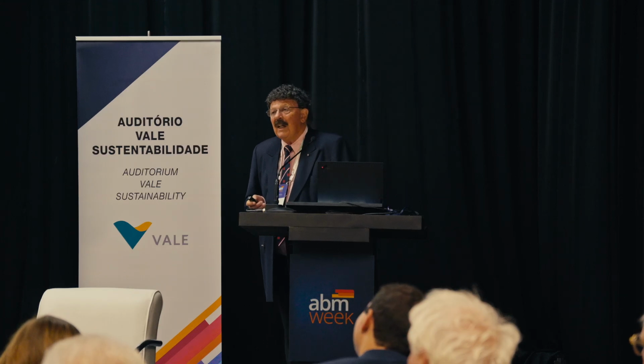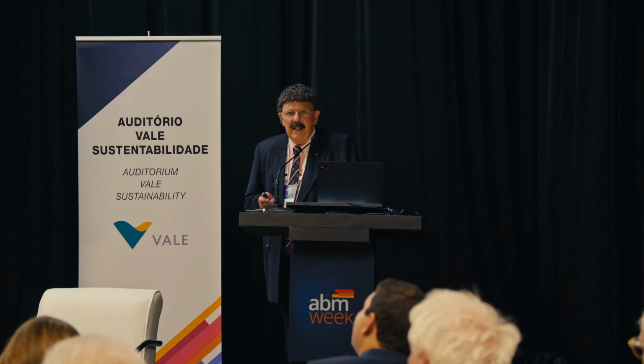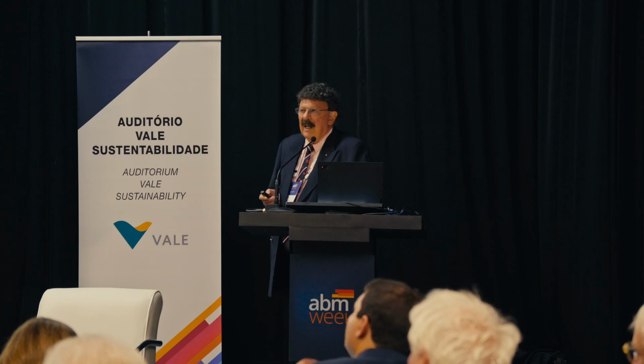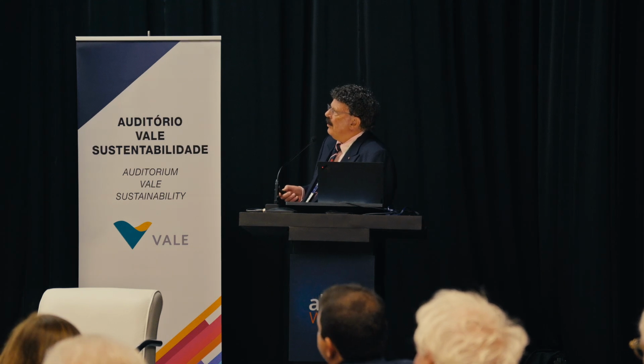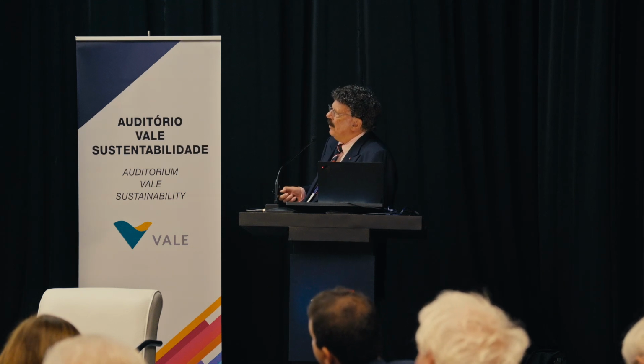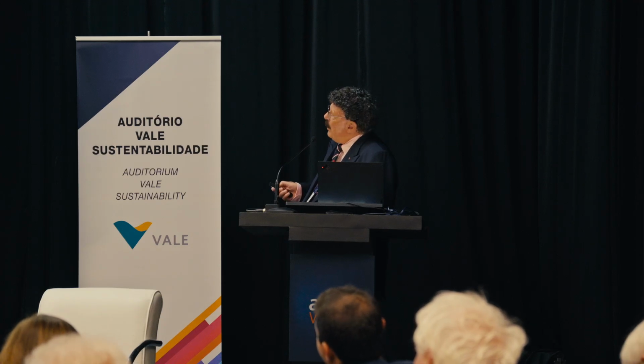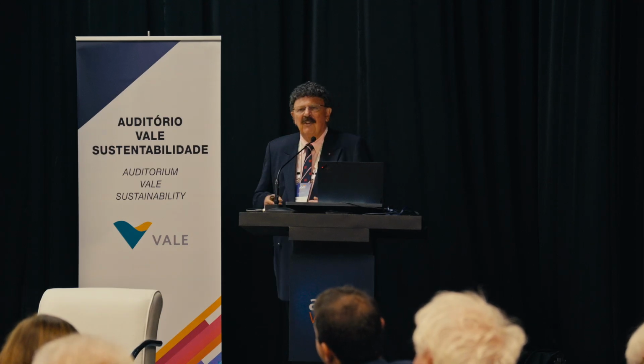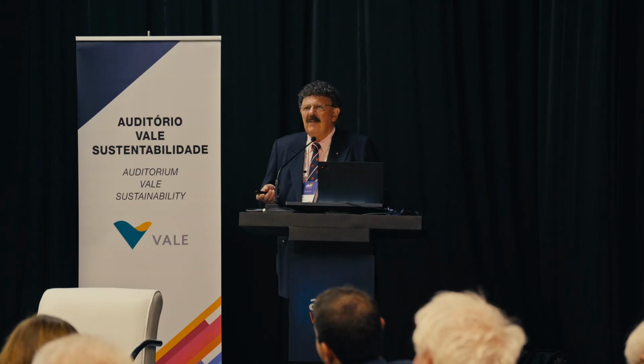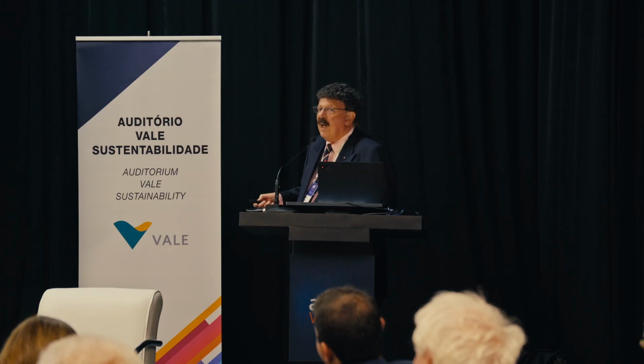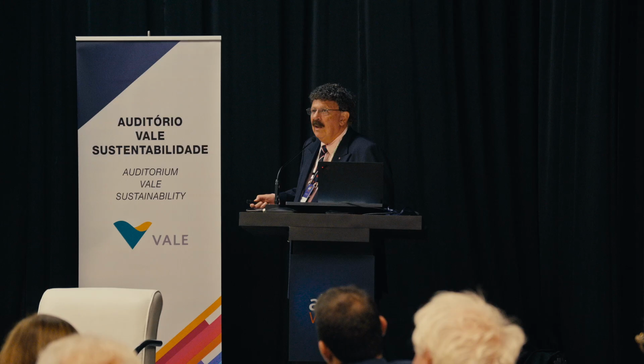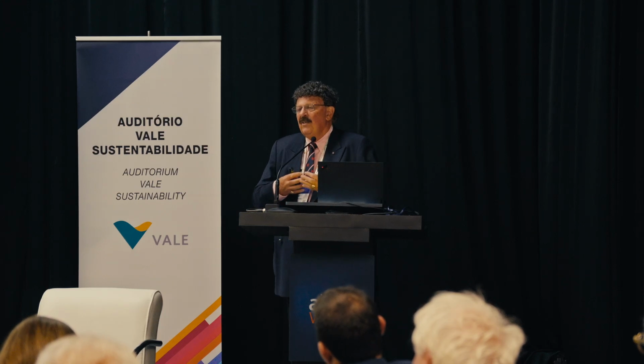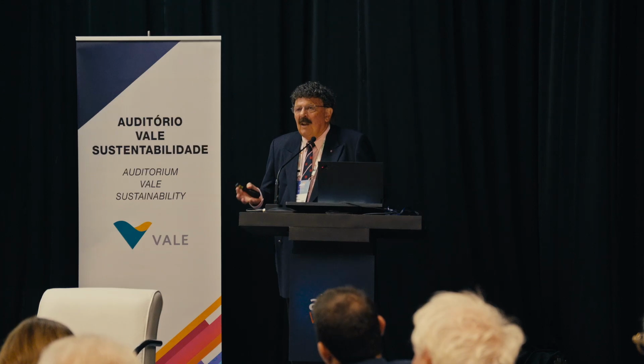So we've even gone to liquid helium temperatures in these materials, and we're still trying to fight over this, but we still get pretty good ductility and very high strength at liquid helium temperatures, which is intriguing. We get an intergranular fracture, so it looks like we have a ductile brittle transition, but the toughness is still 100 megapascal root meters. So that may look brittle, but it certainly isn't. And so this material doesn't even have a ductile brittle transition, and it's body-centered cubic.